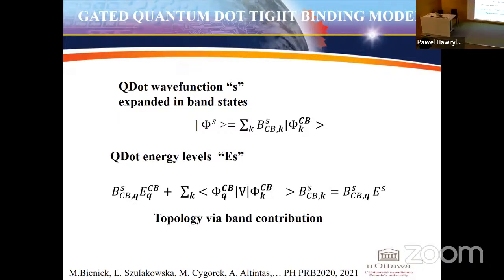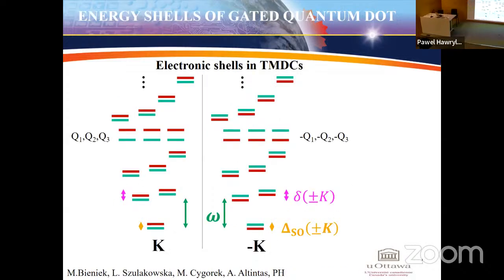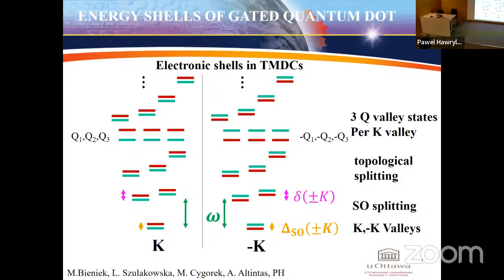And here the potential confining electrons contains topology of the wave function through a band contribution. So these are the spectra. They are characterized by the following properties. There are two non-equivalent valleys. Then there is a spin orbit splitting, so the spin up and spin down states are split. Then there is a topological splitting of states which have different angular momenta. So turning to the right or turning to the left, they effectively sense the topological magnetic moment. Then there are these Q valleys per each K valley that generate another set of states.